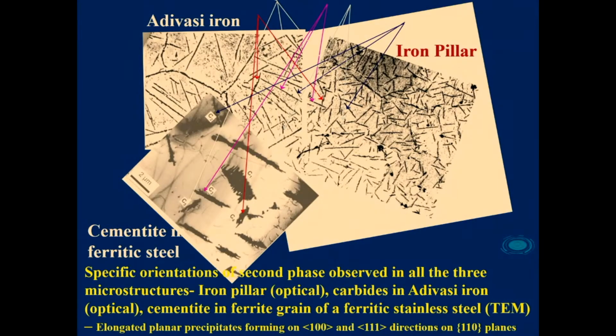And here you see a modern ferritic stainless steel, where from the electron microscopy you can identify the possible orientations of the cementite, and if you align the grains in a particular orientation, there would be a one-to-one correlation with the cementite, which is identified through electron microscope of the modern steel in the ferrite matrix, and the orientations would exactly match. So from the orientation relations, this is the indirect evidence I was talking about. So it is cementite and not related to the phosphorus. But phosphorus is more uniformly distributed, we believe, in the matrix, and that is giving the corrosion resistance.